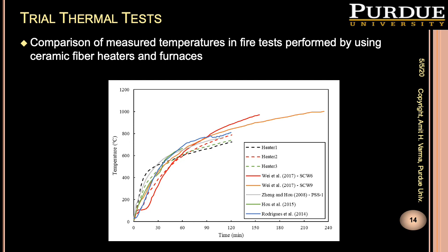So for the unprotected specimen, the surface temperature time curve compares really well with the ceramic fiber radiant heater provided steel surface temperature time curve. The difference between the two heating approaches is that our heaters directly control the steel surface temperature time curve, whereas the furnace tests control the gas temperature, and from that we get the steel surface temperature time curve.